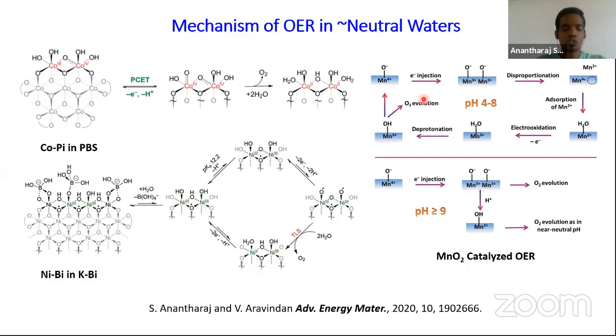And let's move on to the mechanism of OER in neutral waters. So as I said earlier, it can either be lattice oxygen participation or adsorbate evolution mechanism, so we will not worry about that now. This is an example of cobalt phosphate thin film catalyzed water oxidation reaction, where we have cobalt 3 sites, which convert into cobalt 4 sites via proton coupled electron transfer reaction, where a proton and electron are concurrently removed out of the system.